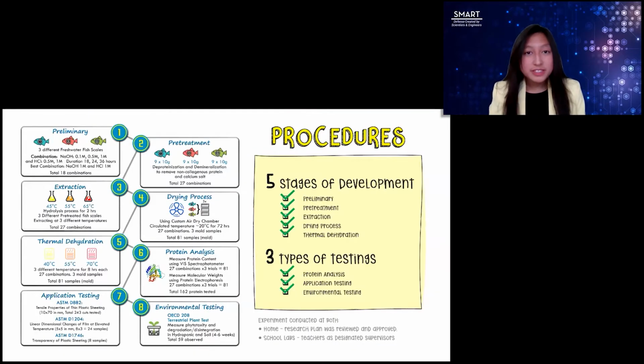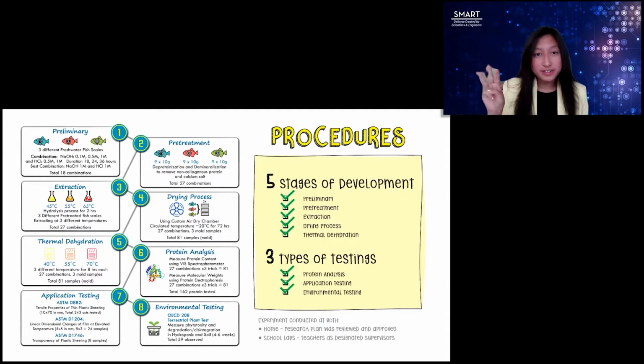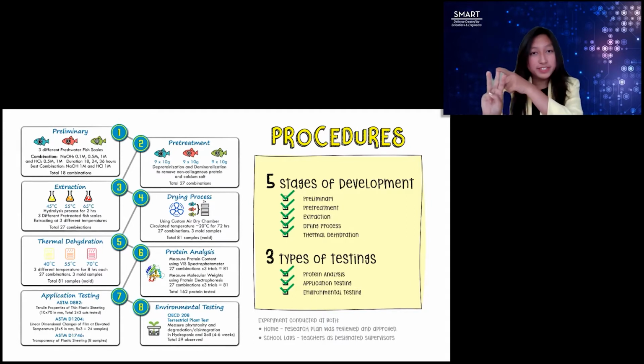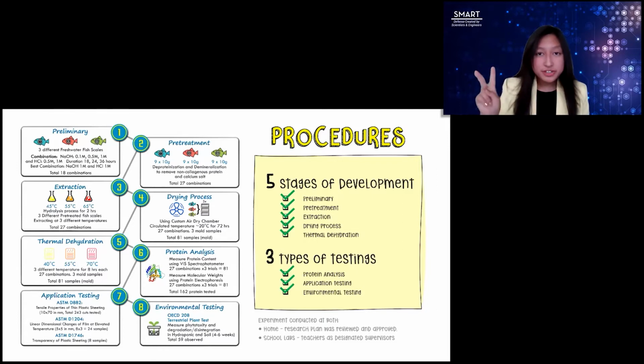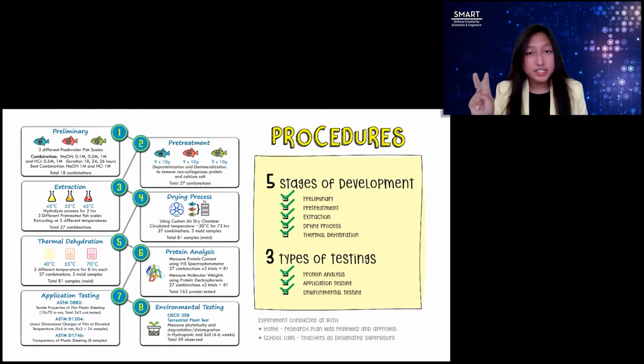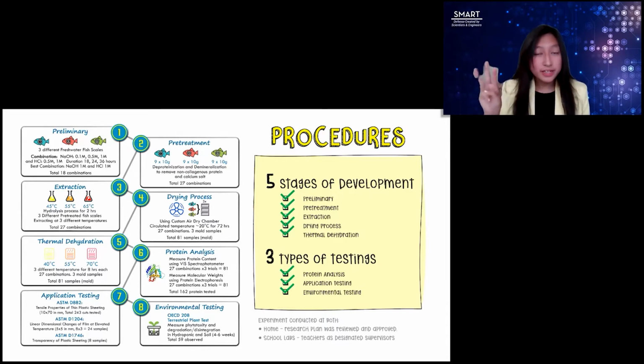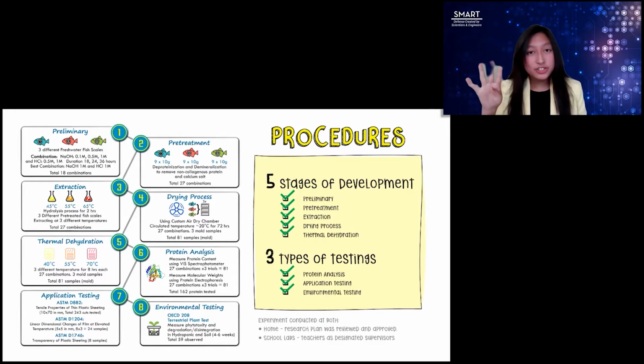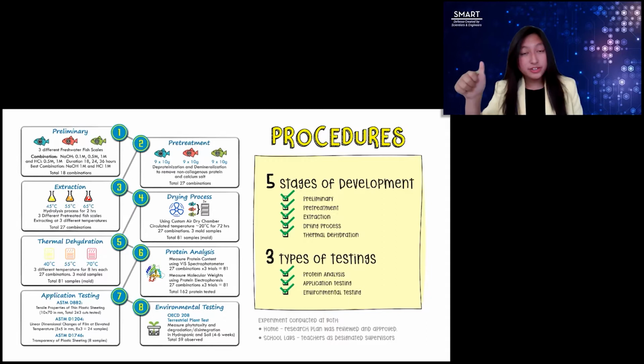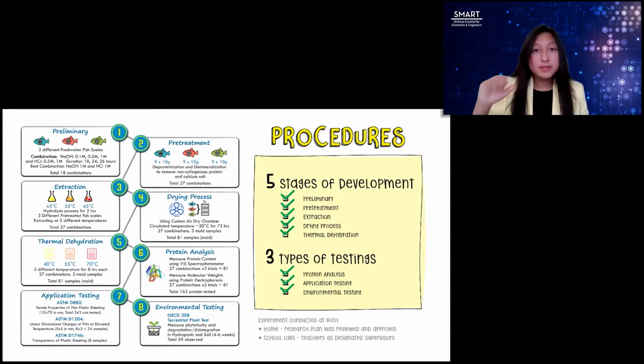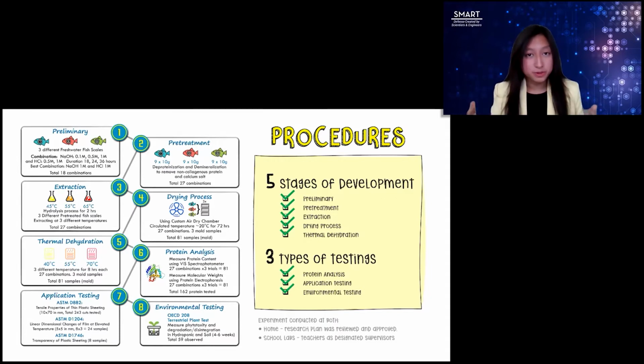So I developed this using 3 species of freshwater fish scales: Nile tilapia, mangrove red snapper, and giant gourami. And I conducted 5 main stages of development. Preliminary, to determine optimal pretreatment conditions. Pretreatment, to isolate the intact collagenous matrix through deproteinization and demineralization. Extraction, to form a thin film matrix. Cooling/drying in my custom cooling chamber to accelerate formation. And thermal dehydration, to enhance the physical properties by removing water molecules and forming thermal bridges.